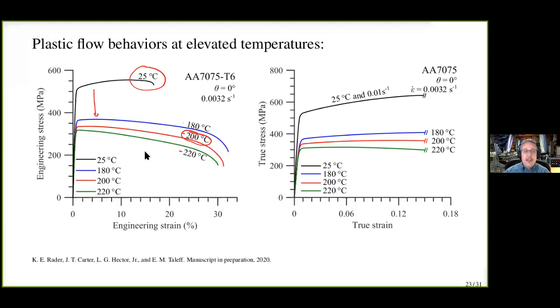So we take the data from this engineering stress, engineering strain plot. We now plot it as true stress versus true strain. And here's our 200 degrees Celsius data. You can see the drop, but surprisingly, this flow stress right here stays almost constant over 0.1, 0.15 strain. So we have almost no strain hardening. That's a very interesting result. And that's important to us because it gives us an idea of how we may be able to predict flow behavior at this temperature. Okay, we'll come back to that in a moment. Let's talk about the ductilities we're getting.